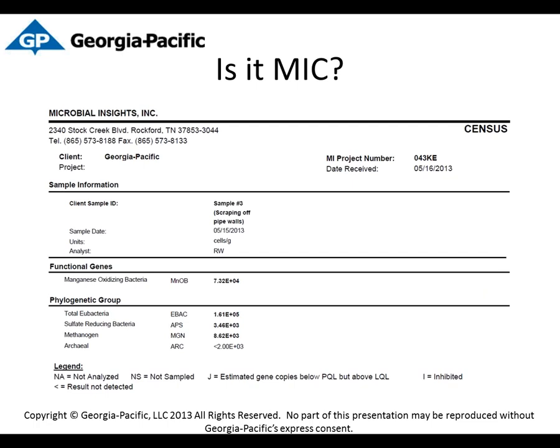And so what we started to look for actually were manganese oxidizing bacteria, one of the first things we looked for. And with Microbial Insights' help and Dora's help, we found that we tested positive for the manganese oxidizing bacteria. We also tested positive for sulfate-reducing bacteria.